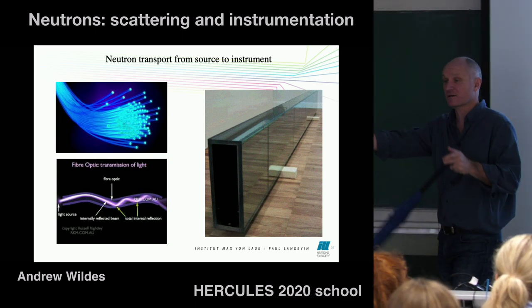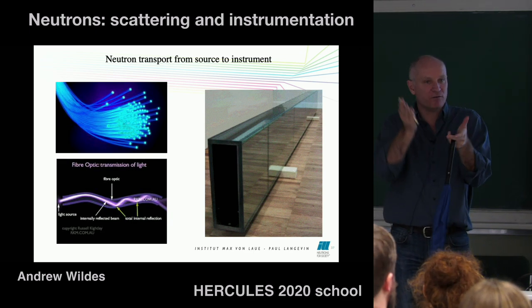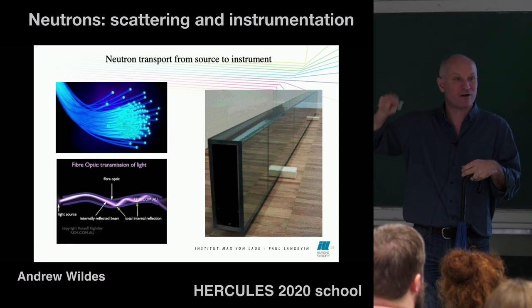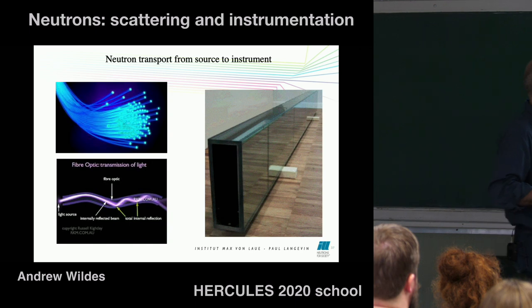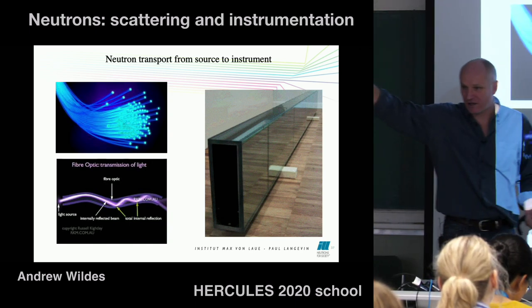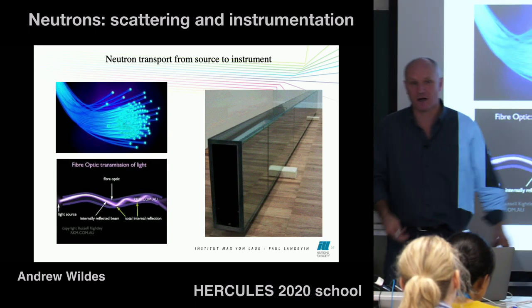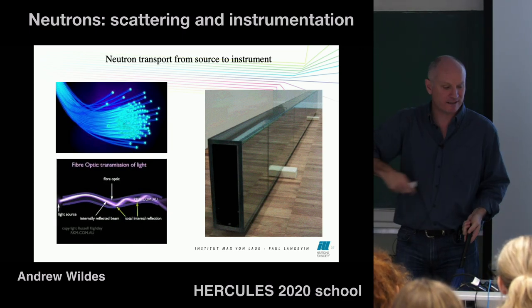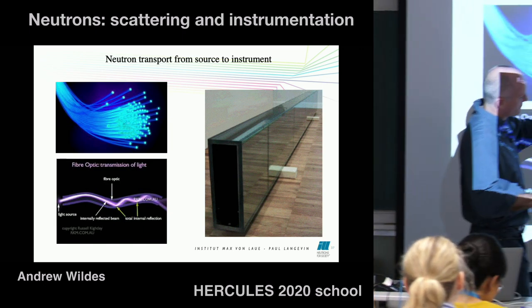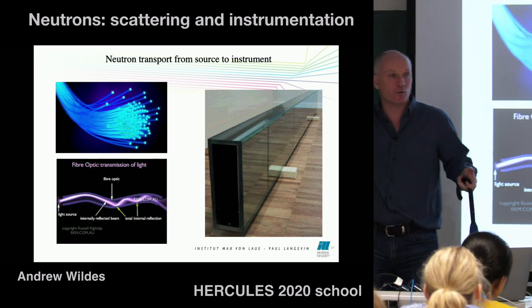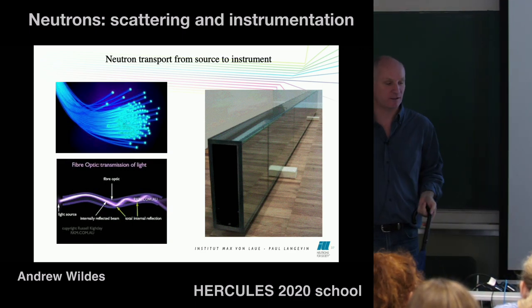It's made out of glass, and then it's often coated with some sort of metal coating to make the refractive index more negative. And then it's evacuated. So the neutrons are going through a vacuum, and then they hit the walls of this guide, and they'll get totally externally reflected. And then you have your source here, you put your instrument up there, and you can put your instrument a lot further away from the source and transport quite efficiently.